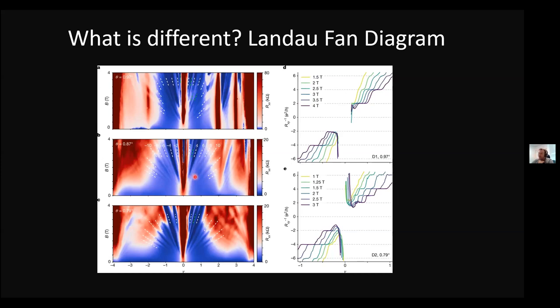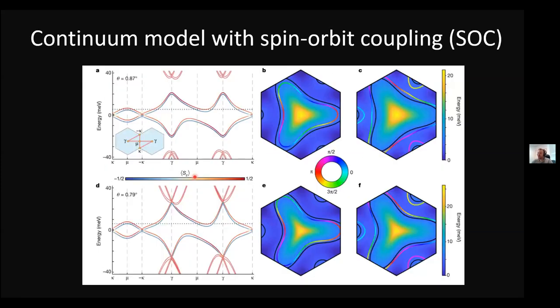So if I think about the band structure for this system, the effects of spin-orbit coupling can be summarized on this slide, where now the flat bands, or not-so-flat bands, are actually modified by the spin-orbit coupling. Depending on what exact type of spin-orbit coupling you put in, these changes are either bigger or smaller.